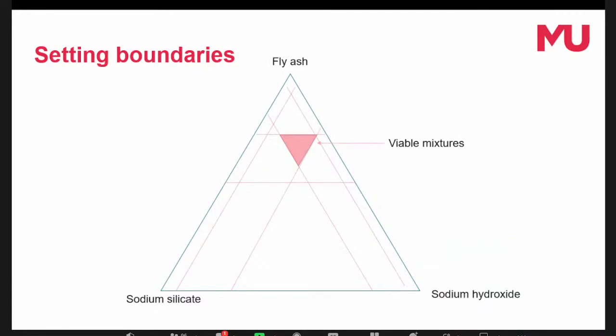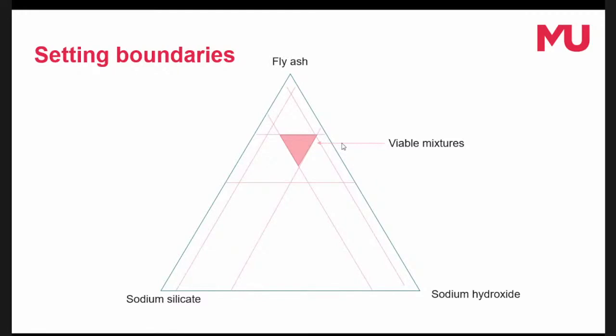If you add too little, it'll just be wet and won't have a cure, so you'll still have wet concrete. If you add too much, it'll just be a powder with no strength. So this pink triangle in the middle here, that is the range of mixtures that we think will give pretty good results. They might not all be very strong, and some might take too long to harden, or might harden too quickly, but pretty much all of them will work in some way. So the challenge then goes from figuring out which mixtures work, to figuring out which mixtures in here work. Much easier.